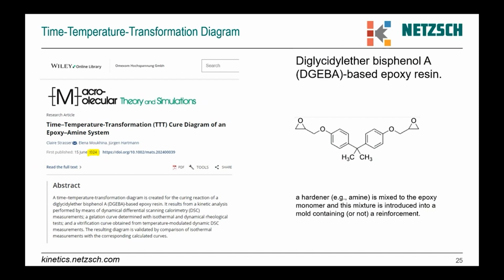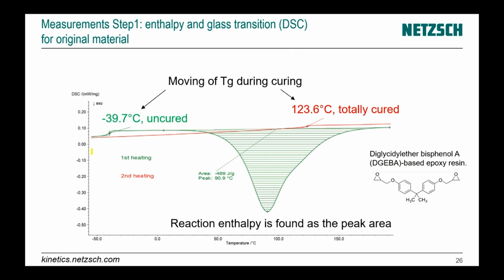And now our next, recent study: the time temperature transformation cure diagram of an epoxy amine system. Here we did a DSC measurement. The first measurement has a glass transition of almost -40. The second heating, for cured material, has a glass transition temperature of 123. It's really a big difference.